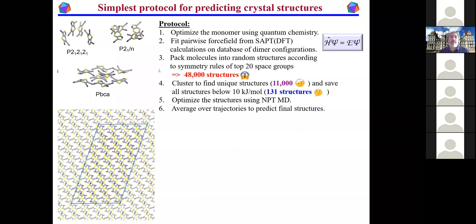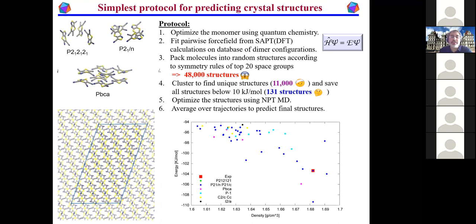You can use then the trajectories that you generate for the ones that remain to get a set of final structures, and then you plot them on an energy density diagram like this, all right? And you can see very clearly that there's a number of structures that appear up here in the high energy, low density range, and these are very unlikely candidates, but then there's a clear separation between a very small number of structures that appear here in the low energy, high density range. And, you know, again, as I said, these differences in energy are on the order of a few kilojoules per mole. Now, this handful of structures down here would be your candidate structures.